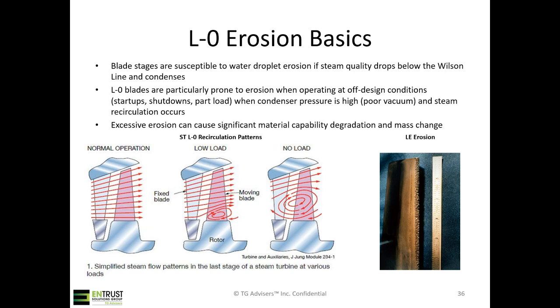So later stage blades, especially your last stages, are highly susceptible to erosion. Any blade that sees wet steam is going to be susceptible to erosion, but your last stages in particular have longer blade airfoil lengths, so your blade tip velocities are higher. You've got more energy being dumped into the blade when water droplets hit it, so it peels off or erodes the edges more quickly as a result. During normal operation, it's not as much of an issue. It's really worse during off design conditions, so startup, shutdown, part load, when condenser pressure is high.